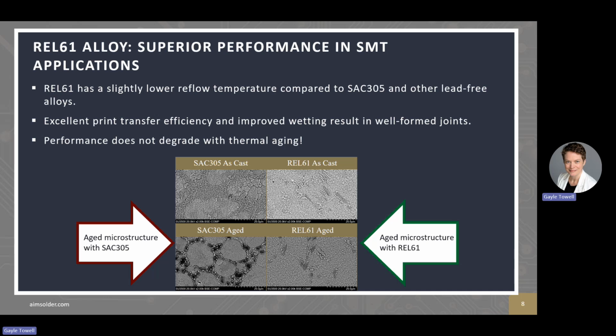REL61 has better performance in general across many applications. So really good print transfer efficiency, improved wetting. Another thing is it does not degrade with thermal aging. The images we see here show SAC305 and REL61 microstructures when they are first cast. After thermal aging, we see that SAC305 develops these structures within it, and those are avenues for cracking and joint failure. REL61, in contrast, does not experience that same change.